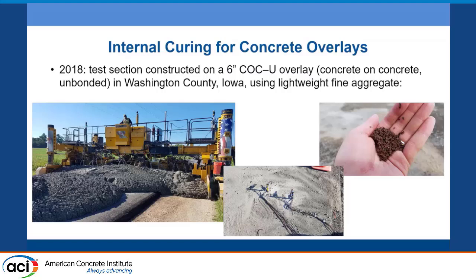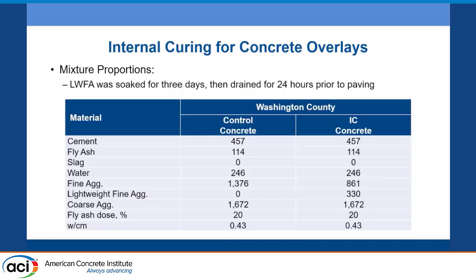And the section was instrumented with temperature and moisture monitors, and they were using lightweight fine aggregate as the form of internal curing. We see the mixture proportions here. These are given in pounds per cubic yard. I do believe it was designed just like the bridge project we were just looking at in Georgia for that 7 pounds of water per 100 pounds of cement. What that ended up being was about 35% of the natural sand that was the normal fine aggregate here was replaced by the lightweight fine aggregate.